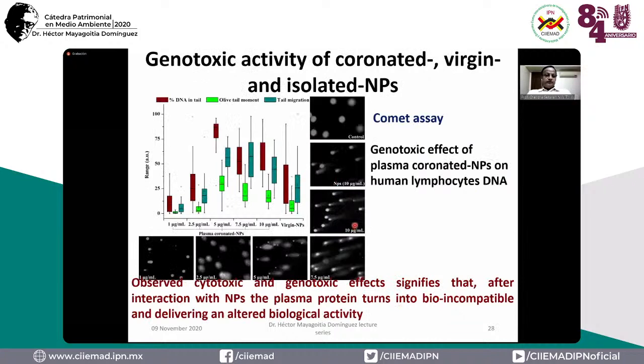We also did a genotoxic activity study using human lymphocytes, and we could see a genotoxic effect, confirmed through the Comet assay, where the DNA tail length was very high. We observed cytotoxic and genotoxic effects, which signifies that after interaction with nanoplastics, the plasma proteins turn bio-incompatible and deliver an altered biological activity. That is also what we could see.